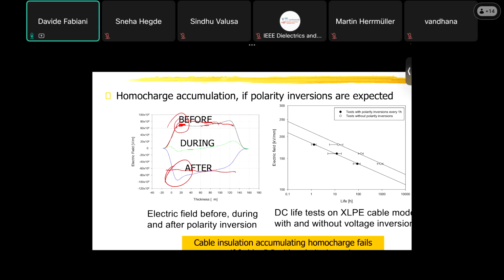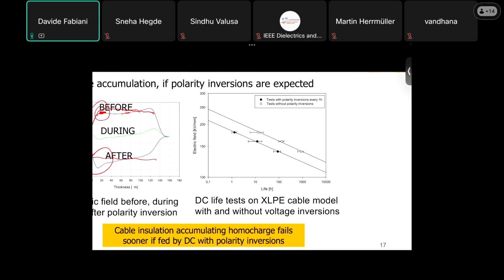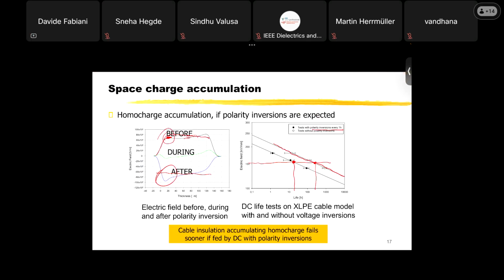insulating material. This is more evident when you do endurance or life tests on your material. For instance, if you do not provide any polarity reversal, you will see that at a given field, this one, 150 kilovolt per millimeter, you have a lifetime of about 200 hours, okay? But if you have homocharge accumulation and you do polarity reversal every 1 hour, at the same electric field you have a huge reduction of life. You see, from 200 to 20 hours. So a reduction to 1/10, one order of magnitude of reduction of reliability, due to the fact that if you have polarity reversal, homocharge can also create problems, okay?